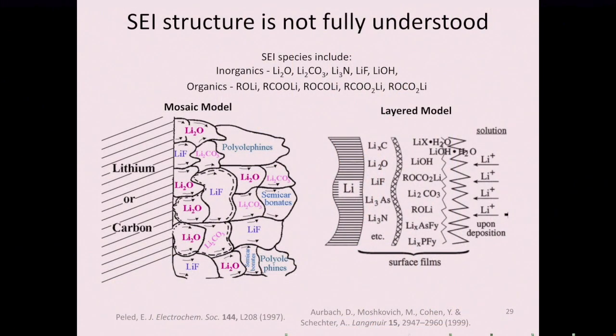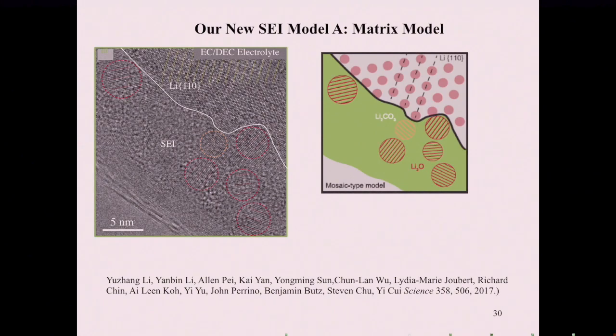Not only that, using a tool like this, we solved about a 30, 40-year-old puzzle. What's the interfacial structure on your lithium battery materials? That can show how fast lithium comes in and goes out, which to a certain degree determines fast charging. Two models of the structure were proposed, the so-called solid electrolyte interface, this SEI, but it turned out it's not like what people proposed. After we could see this under cryogenic electron microscopy, this is a lithium metal. This 20 nanometer thick layer is the interfacial layer, or SEI. And this consists of inorganic grains embedded in an amorphous matrix, different from what people think.